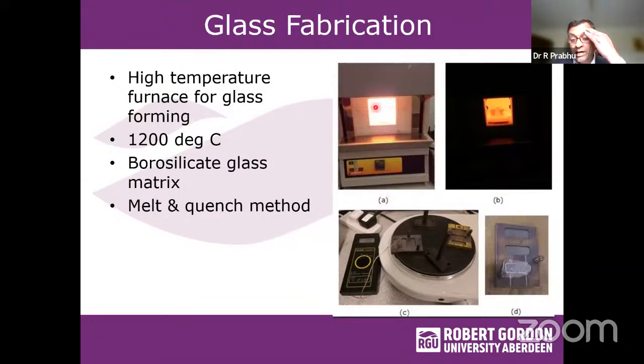You can see the high temperature furnace, and this is through a filter. You can see these ingredients were mixed and put in a platinum crucible to melt the glass, and it was quenched and pellets were made. You can see it's a clear glass, and these glasses are doped with rare earth elements.